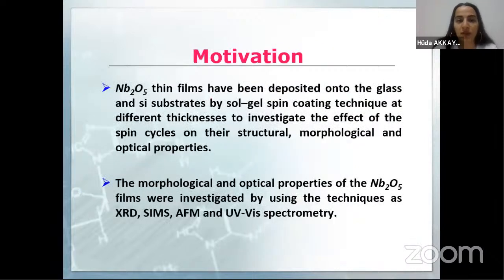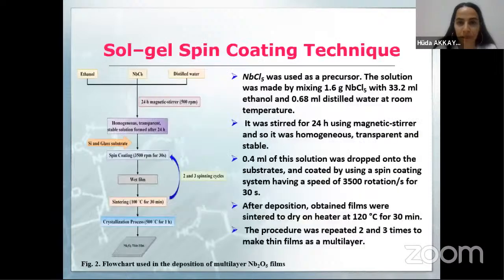My motivations. Niobium pentoxide thin films have been deposited onto glass and silicon substrates by the Sol-Gel spin-coating technique at different thicknesses to investigate the effect of the spin cycles on their structural, morphological, and optical properties. The properties of the niobium pentoxide films were investigated using X-ray diffraction, secondary ion mass spectroscopy, atomic force microscopy, and UV visible spectrometry. This figure is a flow chart of the deposition of multilayer niobium pentoxide films, and niobium pentachloride was used as a precursor.